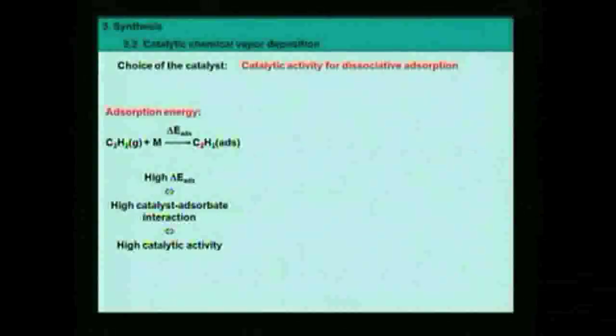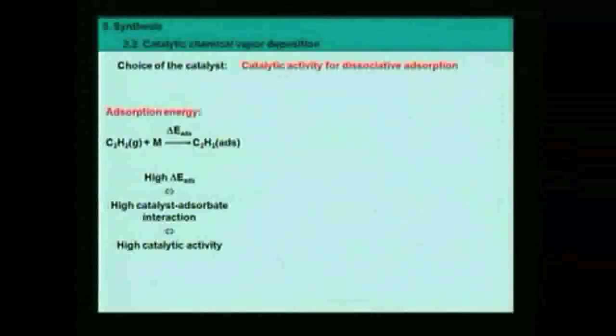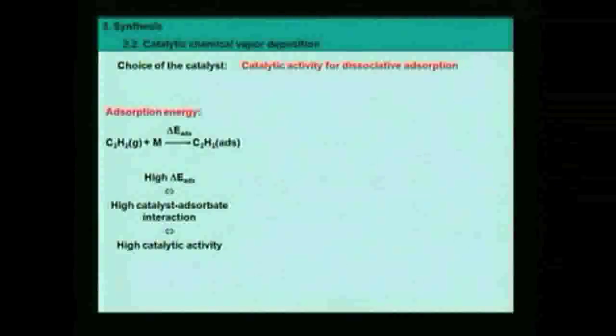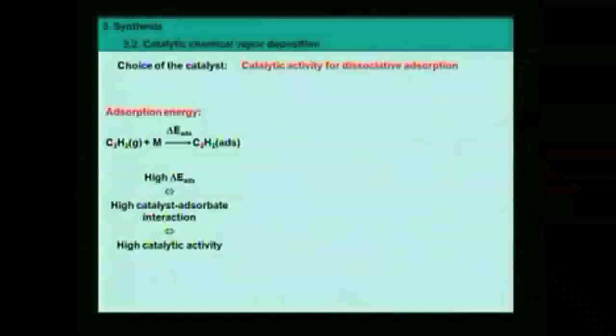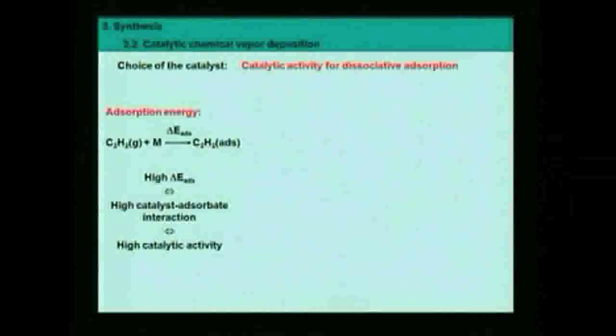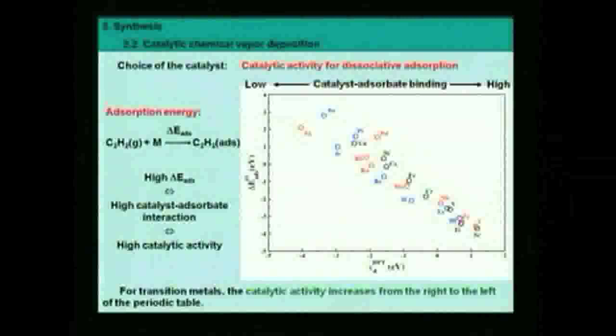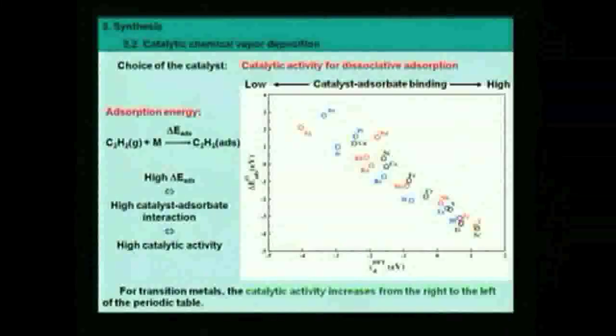How is it observed experimentally to have catalytic activity? Well, a very useful experimental data is the adsorption energy, also called the heat of adsorption, the enthalpy of adsorption, and the adsorption energy is defined like that. It's a difference of energy between this initial state, that is the carbon-bearing molecule in the gas phase, and the adsorbed carbon molecule. How does this adsorption energy, which gives you an idea of the strength of adsorption of the molecule on the substrate, how does this physical value change as a function of the elements?